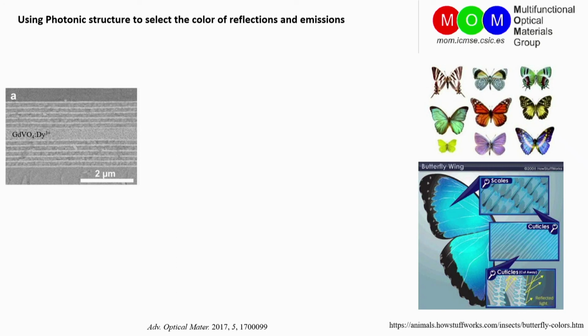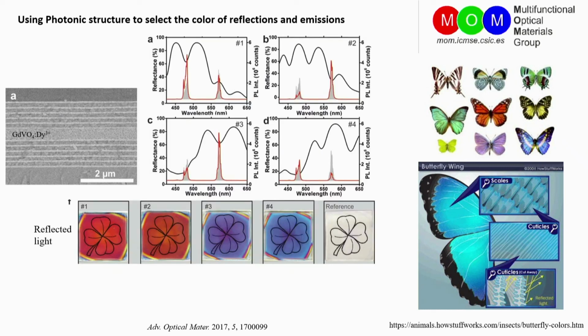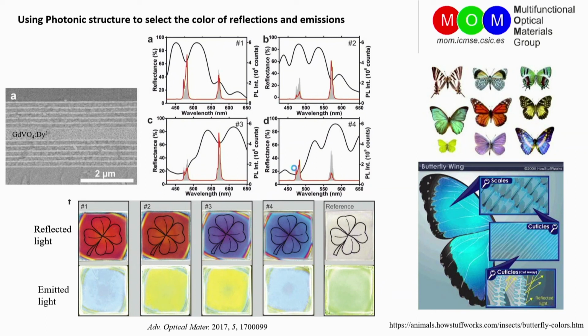Our group also prepares a photonic system to tune the reflected and emitted light. Similar to the butterfly wings, changing the thickness of any layer in this system will change the reflected light. The change is visualized by a black curve in these figures. Due to the change in the reflected light, we observe different colors. The phosphor particles that we incorporate in the systems have two emissions, blue and yellow. Changing the thickness of this system also causes a change in the ratio of intensity of those emissions, which is visualized by the red curve. Due to the change in the intensity ratio of the emissions, we observe different colors in the emissions.